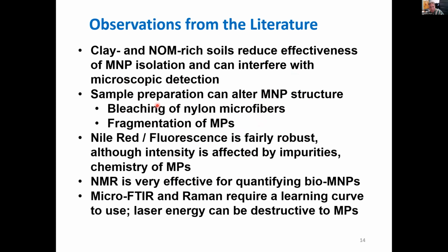The Fenton's reaction, for instance, very commonly causes bleaching if we're working with nylon microfibers that might be coming out of textiles. Also, we can have fragmentation and size reduction, as many of our microplastics are very brittle, and that could introduce an artifact into the data. The Nile red fluorescence technique is very robust, although the response factors can be quite different between plastic polymer types. And often if there are impurities in the matrix as well, that could affect things.